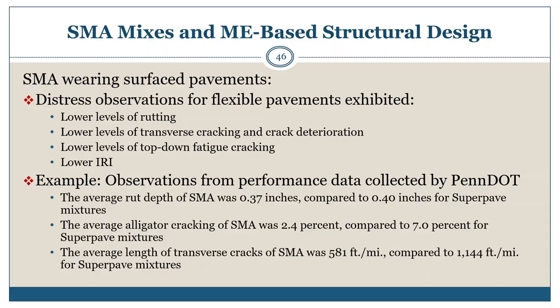and showed the average rut depth of SMA was 0.37 inches compared to average rut depths of 0.4 inches for Superpave mixes. Within that same study, the average alligator cracking of SMA mixes was 2.4% compared to 7% for Superpave mixes, which is a significant reduction in alligator cracking. The average length of transverse cracks of SMA mixes was found to be 581 feet per mile compared to 1,144 feet per mile for Superpave mixes. Also, a significant reduction in the length of cracks for SMA mixtures.